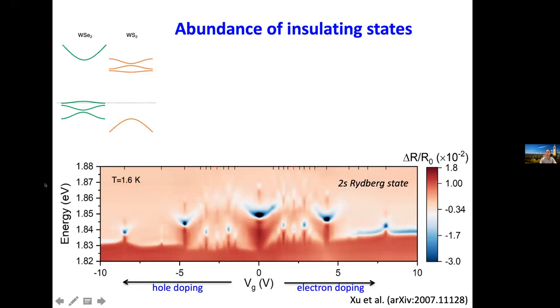So we see many peaks at different energies and different intensities. The highest 2s exciton energy occurs at 0 gate voltage, and this also has the largest intensity. This is the gap of the superlattice, the largest gap in the system.